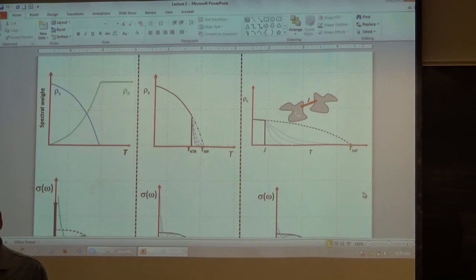So that's what I was saying: from the perspective of the BCS theory, the BCS wave functions, you can solve the problem exactly, you get the right answer, but the underlying physics is completely lacking. So it all appears in these coherence factors. The coherence factors, just as their name suggests, have to do with this coherent superposition of filled and empty states, and the fact that it's the same for all wave vectors. So why does that matter? To me, that was the deep underlying mechanism: this conjugate relation between number and phase.